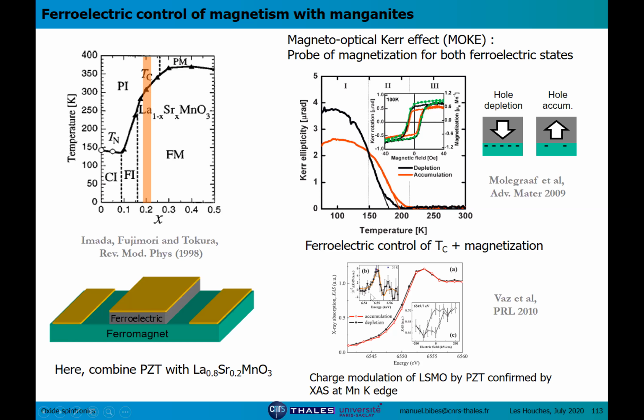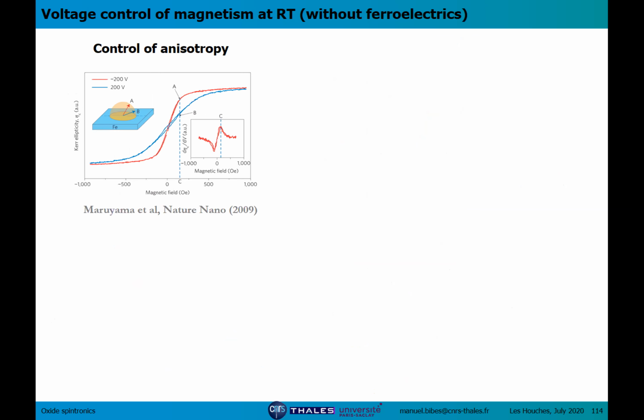In this other set of results from, I think, Charles Ahn at Yale, the same kind of results were obtained, and direct observation of the modulation of the charge density in manganite was also obtained. So I don't think there are very, very spectacular results using ferroelectrics and magnets to control magnetization with very strong amplitudes and at room temperature and remnant effect.